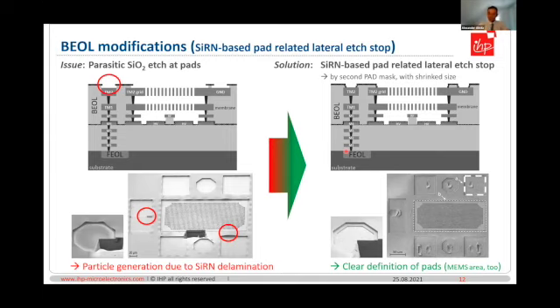A further issue is a parasitic SiO2 etch at pads, where underetched and partly cracked silicon-rich nitride leads to particle generation. I try to highlight this here in this schematic: in the upper part are the pads on top of the top metal 2. And in the images you can see this here. We have an under-etch of the top metal 2 part in the RF pad region, and related to the complete MEMS, including all pads, we have these delaminations everywhere, and here it's already cracked.